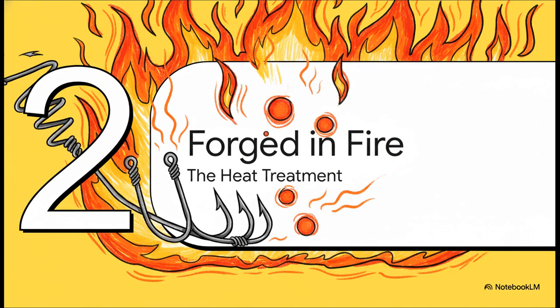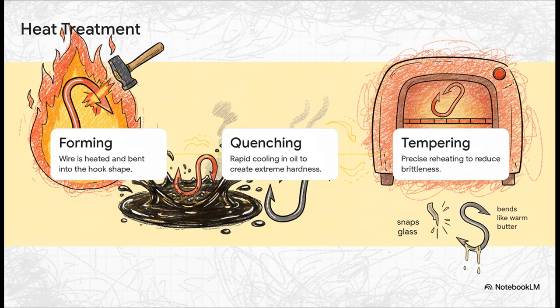Moving on to Section 2, Forged in Fire, the heat treatment process. So, simply having high-carbon steel wire isn't the end of the story. The raw wire has to undergo a highly controlled thermal journey to survive the violent shock of a strike. First, the wire is heated and formed into the hook shape. Second, it undergoes quenching, which is rapid cooling, usually in oil, to create extreme hardness. Finally, it requires tempering, which is a super precise reheating process. Wait, so the factory has to nail this temperature exactly? Absolutely. If they miss the tempering temperature by just a few degrees, the entire hook is ruined. Too low and it snaps like glass, too high and it bends like warm butter.